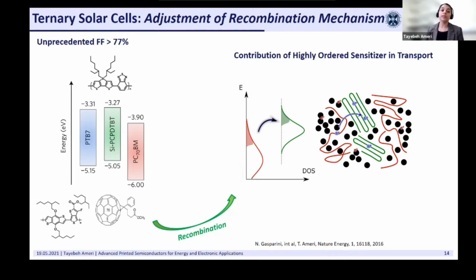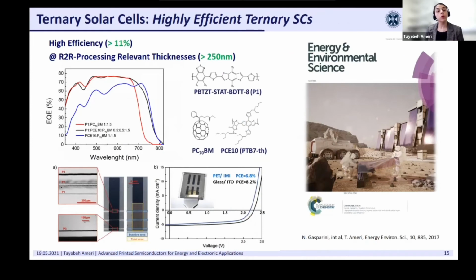And based on all these lessons that we learned on how to design fully functional ternary systems over time, we were able to make new ternary systems with a high efficiency of over 11%, importantly at a roll-to-roll processing relevant thickness of over 250 nanometers, because it's very important for printing technologies to have enough thick films. And this high efficiency encouraged us also to fabricate the modules.